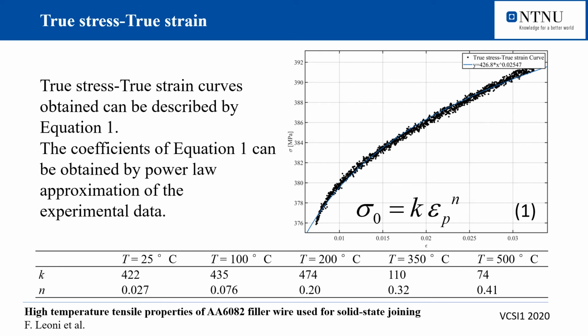True stress to strain curves at each temperature can be calculated. These curves, which show how the plastic flow varies with the accumulated plastic strain at different temperatures, can be described by the equation shown, where N and K are the strain hardening coefficient and the strength coefficient respectively. The table presented here summarizes the values of N and K obtained following the fitting of the equation to the experimental true stress true strain data.